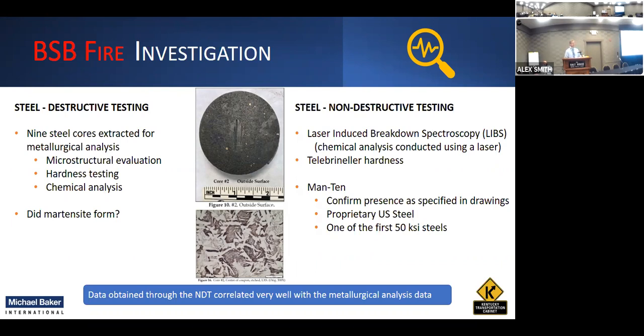One of the things that we found in doing this was that much of the steel was what they call a Man-Ten steel. That's a high manganese steel. That additional manganese in the steel increases the carbon equivalent and makes it a higher strength steel. It was a proprietary U.S. steel from the early 60s. It was one of the first 50 KSI steels that came out on the market at that time. So many of the main structural members of the truss and the floor beams were actually out of this Man-Ten steel and not a lower grade steel.